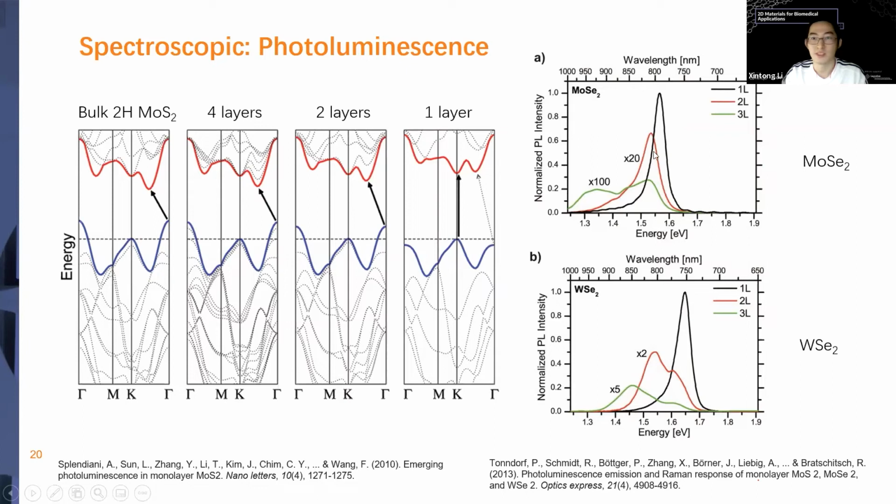So for monolayer, it's much bigger, and the peak position also changes, because for bilayer and trilayer, these peaks correspond to the indirect transition, which has smaller energy than monolayer. So with this method, we can determine the layer number, whether it's one layer, two layers, or trilayer, very thin layers, very conveniently without having to do other measurements like AFM or anything like that.